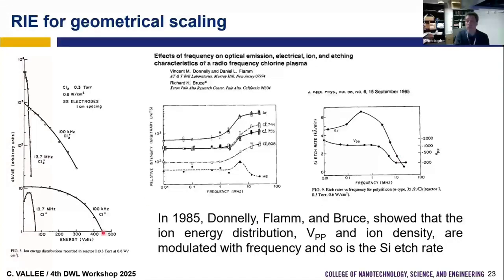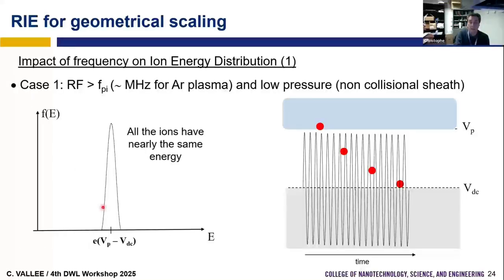And you not only decrease the ion energy, you can also, with the frequency generator, modify the shape of the ion energy distribution function. If you have a high frequency generator, you have low energy ions with a narrow distribution, while if you use a low frequency generator, you have energetic ions with a large energy distribution. So to try to understand this shape, I did a very simple schematic.